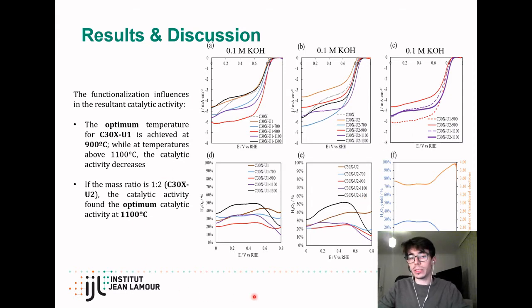Regarding the selectivity that governs this oxygen reduction reaction, we can observe that there were no important differences regarding the carbon-urea ratio, and the most catalytic sample in figure F saw a number of transferred electrons close to 4 during the whole potential range.